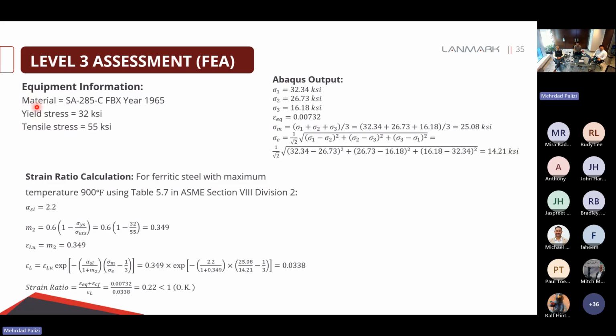So the first thing is we should know what type of material we are working with, what is the yield stress and tensile stress for that material. Actually, we need the ratio of yield to tensile stresses. We also have some outputs from our finite element software. We've got the principal stresses and also the equivalent plastic strain. So what we do is we calculate the average stress, the von Mises stress, and then we calculate the ratio of the average stress to von Mises stress. Actually, this is an important variable. It is called the stress triaxiality. In many failure criteria, you might see this ratio.